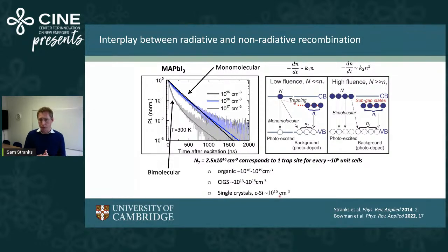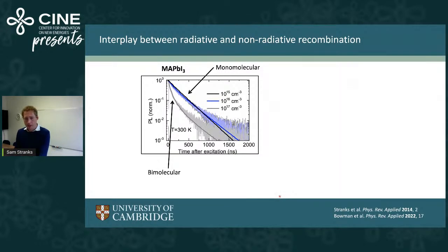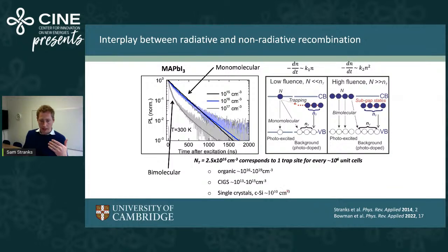And this is really another example of this defect tolerance of these materials, where we see that they have quite a high density of defects, but in terms of performance, they're still relatively comparable to some of these very high performance semiconductors like silicon. This is because silicon and gallium arsenide materials like this are not very tolerant to defects. So you really need to have extremely low levels of defects for them to operate well.